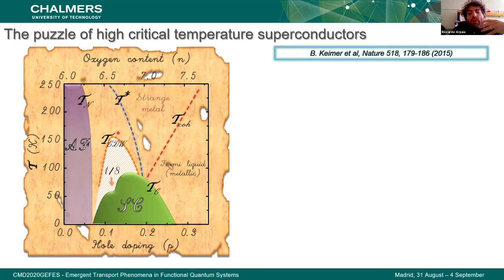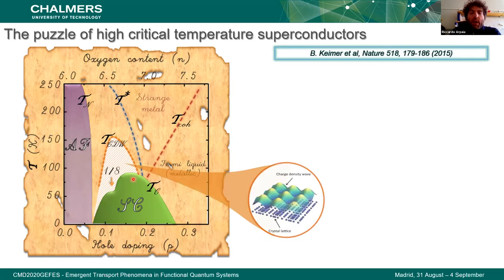Below this temperature, we know that different intertwined orders, among which there is also charge density wave, characterize the ground state of this material. So what happens in the charge density wave region? The experimental evidence was only produced recently, thanks mostly to the development of resonant inelastic X-ray scattering. This region is characterized by valence electrons lying in the copper oxide planes, which tend to segregate into periodic modulations that are incommensurate with respect to the unit cell.